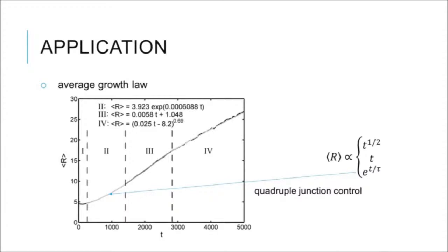And the result you can see here. We have again a short initial period of time, and then we observe an exponential increase of the average radius as a function of time. After a couple of hundreds of Monte Carlo time steps, we see that the curve changes, however. This exponential regime is marked by number 2, and then we go over more into 3, which is a linear regime, and finally it tends to go back to the square root.